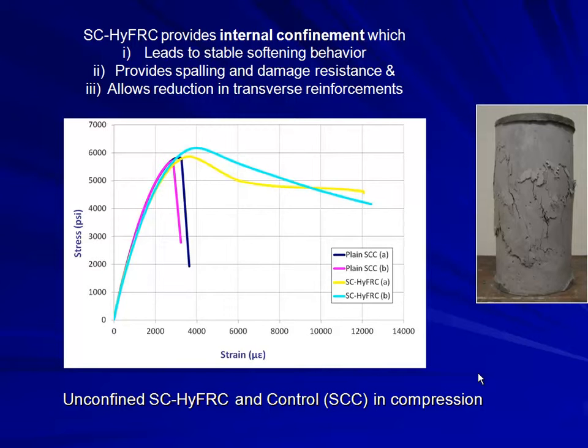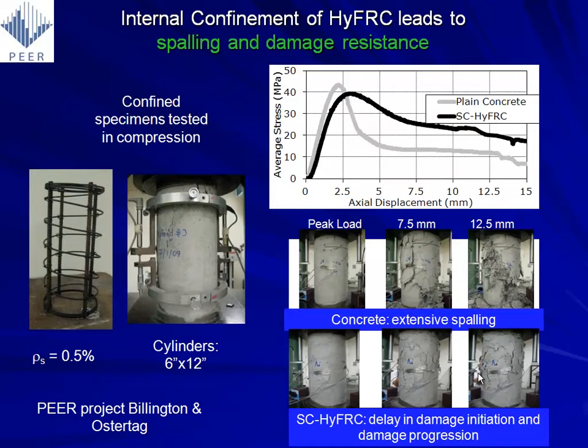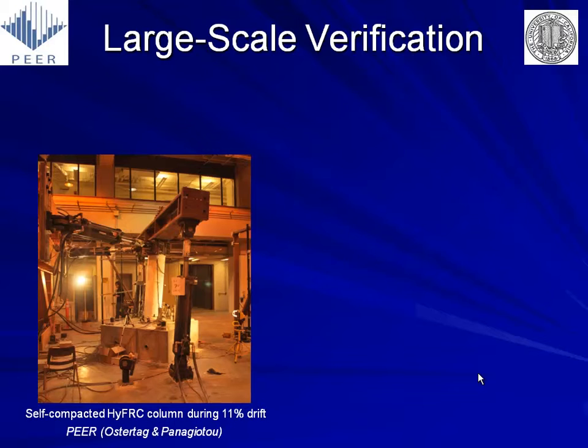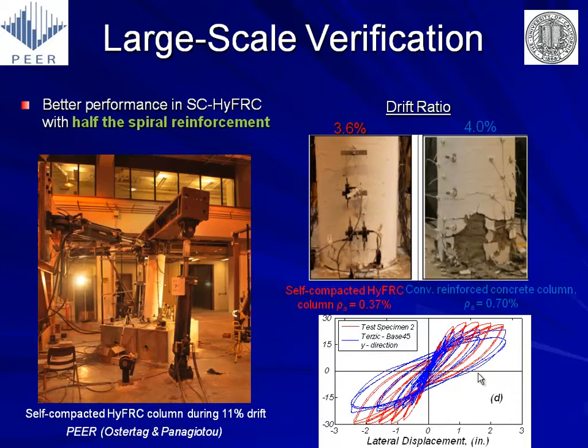And when you see the damage here, you see that you have much less damage. For example, this is your concrete. You see extensive spalling. This is your stress versus axial displacement at different positions, right at the peak load at 7.5 and 12.5. You see very, very large damage in your control specimen. You see much less damage in your self-consolidated hybrid fiber reinforced. And of course, we could validate that with the large-scale verification of the columns. And I just want to point out that this kind of damage resistance was really half the spiral reinforcement.